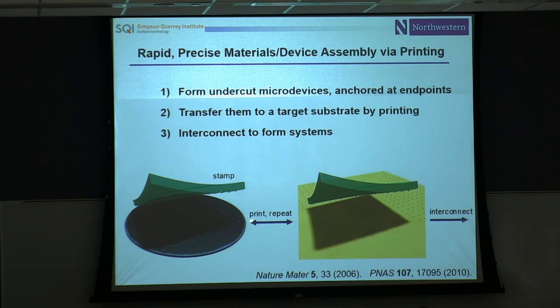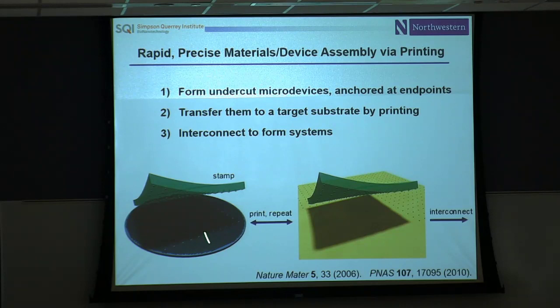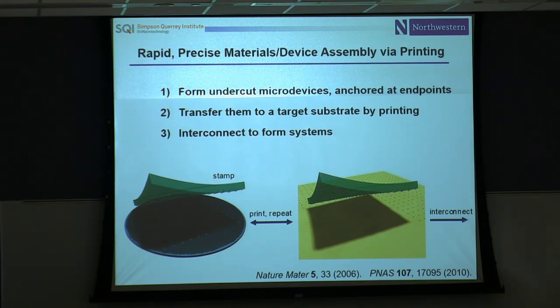We've taken a different strategy inspired by soft lithography—not printing molecules, but printing semiconductor nanostructures. Because they're generated from a wafer using a lithographic process, you know exactly where those membranes or ribbons are located. You take a stamp, use that pre-processed wafer almost like an inking pad, bring the stamp into contact, lift it off, and end up with inked regions on the raised features of the stamp. Then you index the stamp over the target substrate and deliver these material elements in a highly controlled, high-throughput manner—hundreds of thousands of individual nanoribbons in a single print cycle.